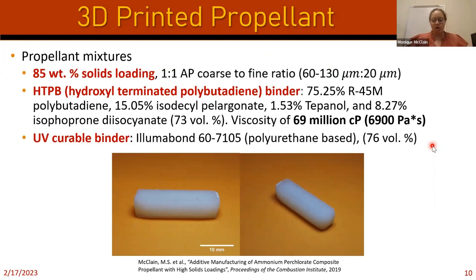So we had this new promising technique. Okay, let's go print some solid propellants. So we went ahead and started doing that. We printed two different types of mixtures. And the important thing about the study was that we showed that we could print a traditional type of propellant mixture without including solvents that have to be evaporated out later or other additives to make it more shear thinning than normal. That was also an advantage of this paper.